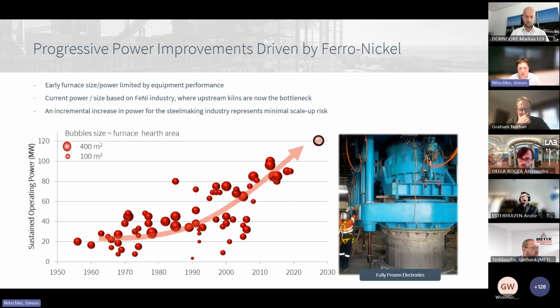without significant technology risk. That smelting intensity is typically compared on a kilowatt per square meter of hearth area basis for electric smelting. And otherwise, this limit is certainly within the current density the electrodes are capable of handling for 120 megawatt operation. And certainly at that 400 square meter mark of physical furnace size, well within the hearth smelting intensity limits as well. So I'm certainly confident that the scale is within reasonable technical risk profiles moving forward.